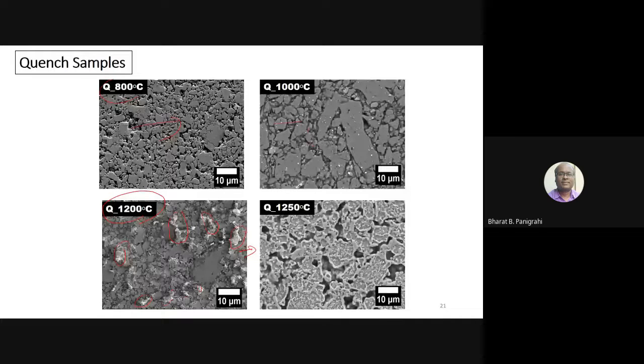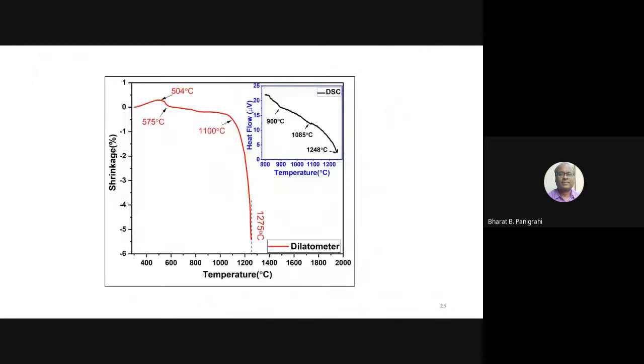So you can actually capture this event by using what is happening in the shrinkage side by dilatometer, what is happening in the thermal profile in the DSC, and what exactly it looks like in the SEM. So SEM, DSC, dilatometer, and XRD can actually tell the complete history of the changes happening in your alloy. Okay, so this I have already explained.